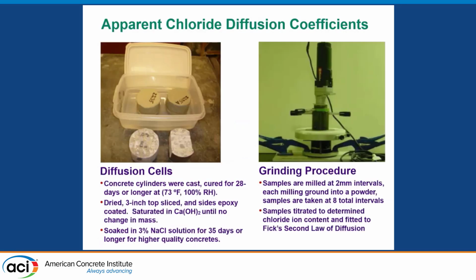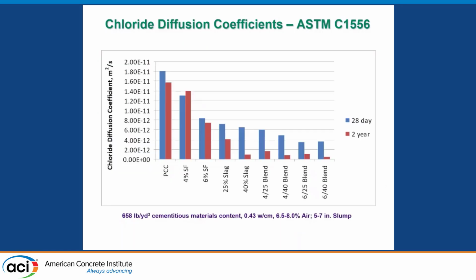This was where the apparent chloride diffusion coefficient was done. We looked at the diffusion cells. There was a grinding procedure. I'm not going to belabor this point. I think it's more important to look at the data when we look at the coefficients. So when we look at these coefficients, this was a 658 mix again, with a 0.43 water cement ratio. Air content was about 6.5% to 8% for these specimens. The slumps were all maintained between 5 and 7.